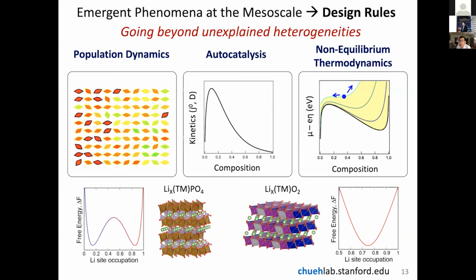The second part of the talk, I will take the opposite phase behavior, which is for a layer oxide. So this is lithium cobalt oxide or lithium nickel manganese cobalt oxide and so forth. And this is a two-dimensional material with van der Waals gap for conducting lithium. And this is another commonly used lithium-ion battery electrode, typically used for high energy applications for electric vehicles and consumer electronics. In contrast to lithium iron phosphate, the layer oxides have mostly a single phase behavior in the regimes of interest, which means it doesn't have a double well inside for the free energy diagram, it has a single well.